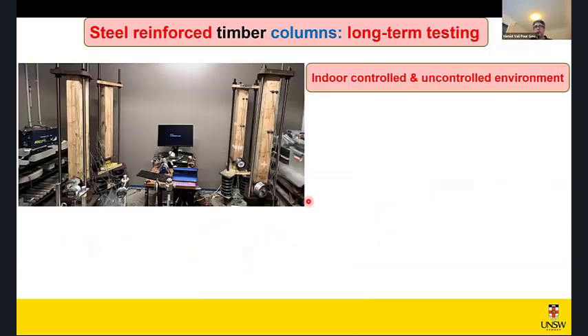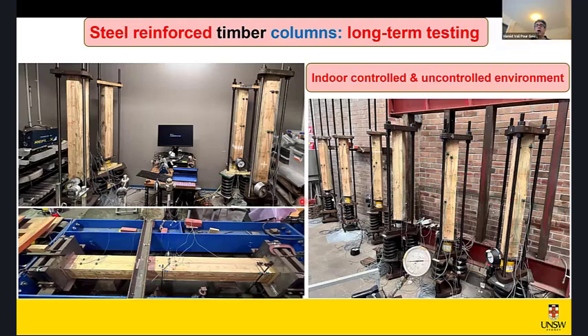We did long-term tests also on the columns to see what's the long-term performance. It's indoor controlled environment and indoor uncontrolled environment. This is the uncontrolled one, and this is the controlled one. It means that we kept the relative humidity and temperature in the room constant for nearly 16, 17 months to see what's really happening. And then we put the same columns in the lab environment. So we couldn't control relative humidity and temperature in this case, and we compare the results to basically separate the creep effect from the mechanosorption effect and the variation in the relative humidity and temperature.